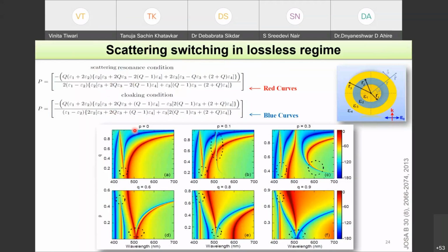P is nothing but R1 over R3. R1 is the core radius, R3 is the outer radius, and Q is nothing but R2 over R3, which is the radius of the dielectric layer over the outer radius. And what are the red curves here? The red curves show you scattering resonance. The blue one shows you cloak state or low scattering state.